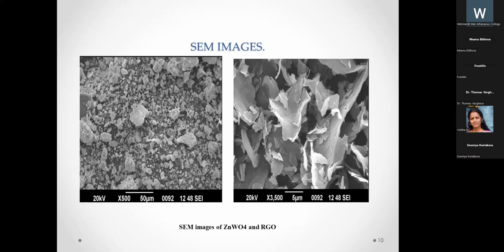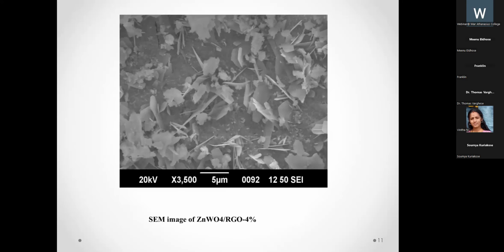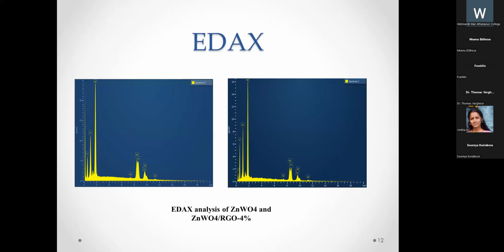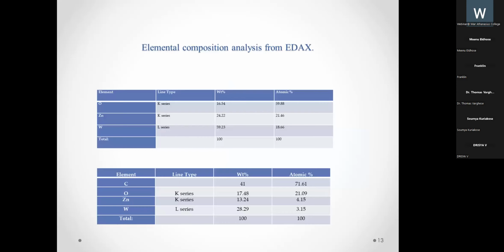These are the SEM images, and from these images not much information can be derived, but we can see the coating, meaning the material is dispersed on the surface of RGO. This is the EDAX pattern analysis of zinc tungstate and zinc tungstate RGO 4%. It is clear that for zinc tungstate, the elements zinc, tungsten, oxygen, etc. were present. But in the case of the zinc tungstate RGO composite, carbon as well as oxygen is also present. In addition, the intensity has slightly increased. And this is the elemental composition from the EDAX pattern.